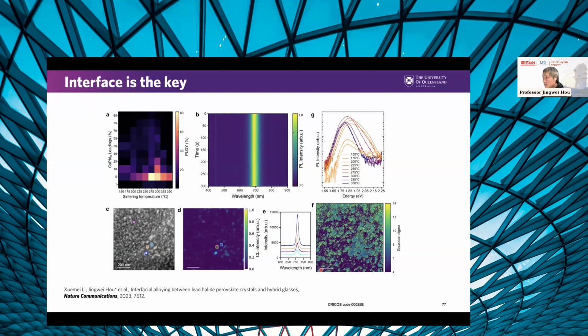And we are very lucky to work with a team of very advanced TEM experts. They actually use cathodoluminescence, which lets them look at the light emission of the nanomaterial under the TEM. By fitting the peak, we can immediately see that this region is all the perovskite phase. That's where it becomes really bright. If you look at the peak width, the peak width at the interface is somewhat broader. This indicates that the interfacial properties must be different from the bulk.